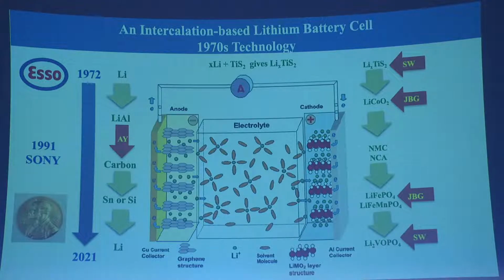John also found out that LFP, lithium iron phosphate, would also take lithium in and out. But you're carrying a phosphate group, so that again reduces your energy. So what we've been looking at is, if you reduce the energy and you want to use a phosphate, phosphate is much more stable, so it's safer. You've got to try to put in 2 lithium ions. So I'll show at the end where we're managing to use vanadium, where you can go from vanadium 3 to vanadium 5 in a reversible manner.